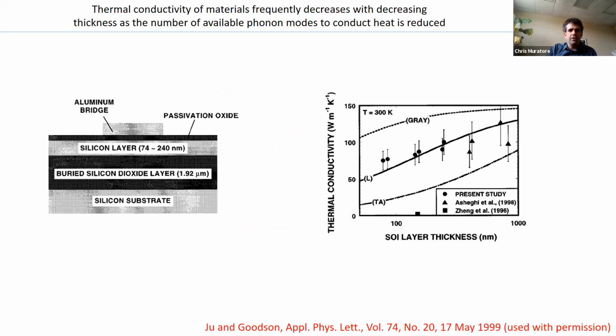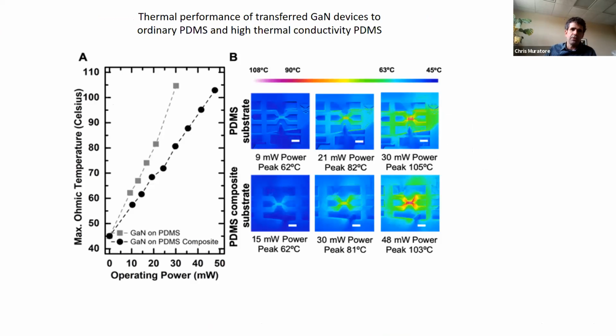One thing we need to be careful about: I love nanotechnology, but when you have things that are nano size, they tend to trap heat because the heat needs to propagate over some distance. There's a characteristic length associated with phononic heat transfer, atomic vibrations, which occur when you have a material that's not electrically conductive. This mean free path is often on the order of nanometers, so if you have very tiny features and tiny materials, you can inhibit thermal conduction through this material. But one thing you can do is just make the flexible substrate a little more thermally conductive, and it doesn't take much to make a big difference in device performance and lifetime.